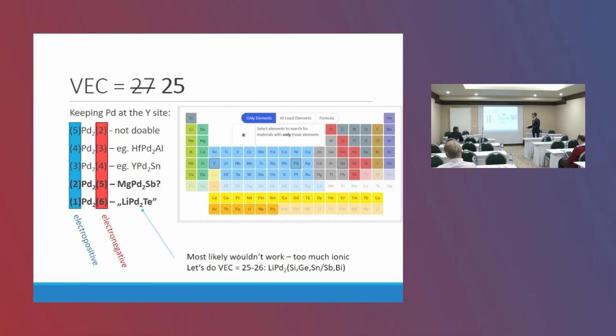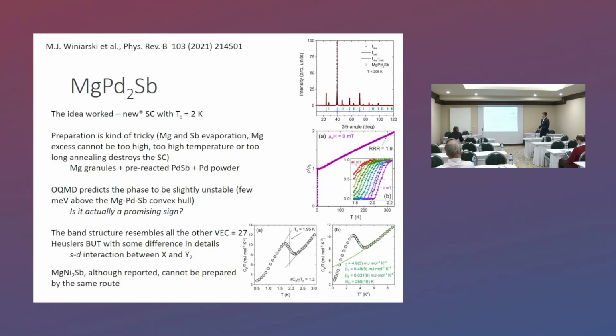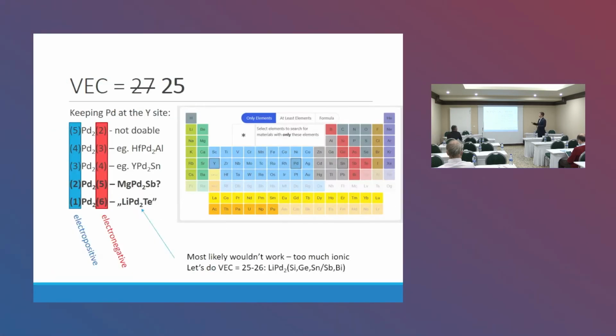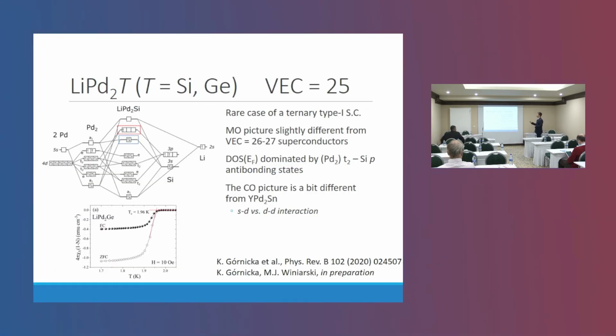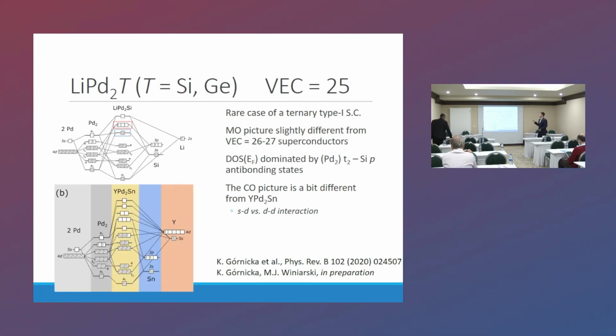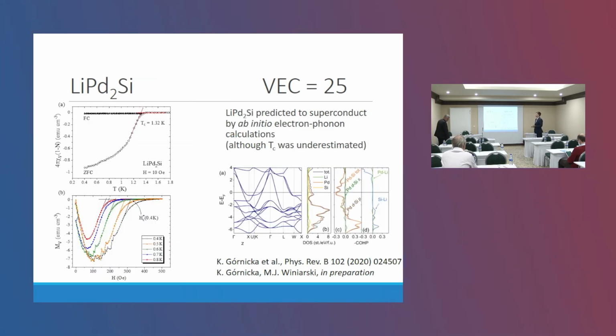But if we decrease our expectations of valence electron count to 25, it actually gives us a superconducting material, lithium palladium germanium, which is a very rare case of a ternary type 1 superconductor. Okay? And again, the density of states at the Fermi level is dominated by anti-bonding states. The silicon analog was actually predicted by our calculations. We found it after measuring it in helium-3.